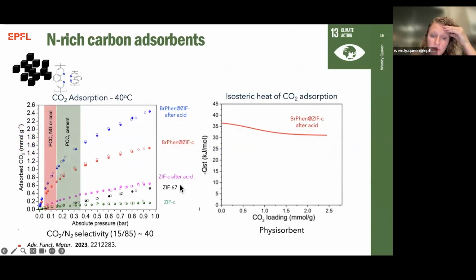So here, I'm just showing you the parent MOF in black. You see it's got a very low CO2 adsorption. We carbonize that MOF. It's still got a very low CO2 adsorption. And then we treat it with acid to leach the metals out. Still, again, the CO2 adsorption is not adequate. However, when we functionalized it with this bromophenanthroline, which helps form this high density of micropockets in the material, we see significant improvements, particularly after we remove the cobalt, which frees up these really nice micropockets for the nitrogen or the CO2 to bind in. And so we see really nice capacities for these carbons. It's about double what we've been able to find for any commercial carbons on the market.